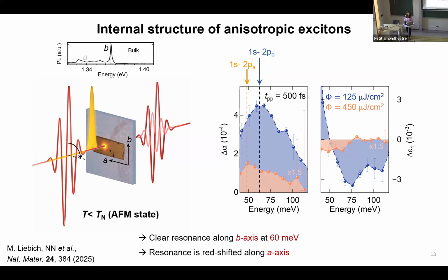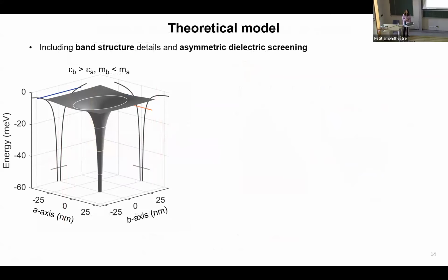is removed. In order to further verify our experimental observations, we had the support from our theory partners at the University of Michigan, who developed a many-body theory and calculated the excitonic wave function in the presence of a highly anisotropic band structure and a highly anisotropic dielectric medium. In such an anisotropic electronic environment, the excitons are bound to a Keldysh-like potential, which is equally anisotropic, and it extends along the B direction.